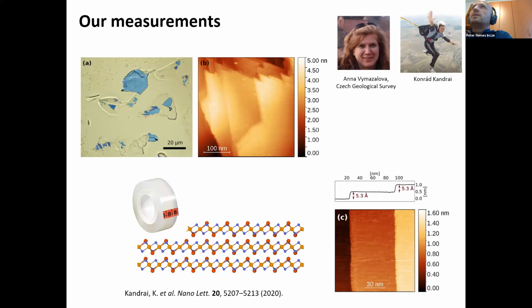Here I have to say a very big thanks to Anna for providing us with a lot of samples and working with us very closely to try to improve the crystals. Most of the STM measurements that I will show you have been done by Konrad, my student in my group. So here you can see some images of this material. What we did is take the material from Anna and exfoliate it with Scotch tape onto a gold surface, which makes STM investigation easy.